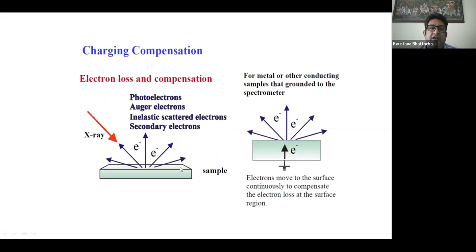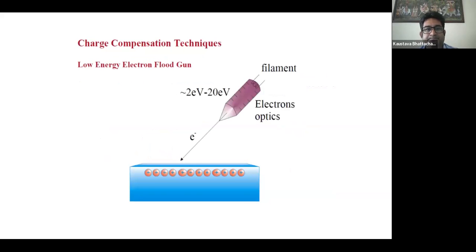Now there is another thing called a charge compensating tool. If my surface is charged, we can use this charge compensating tool to give some electrons or to take away some electrons. I mean, it usually gives only electrons. For example, there are several polymeric materials which are not amenable to XPS at all. For those, we require this tool to provide some charge so that we start getting electrons. And if the surface is overcharged, say we have a charging of almost 3 or 4 electron volts, we give a charge compensation so that we have a proper value of the binding energy.